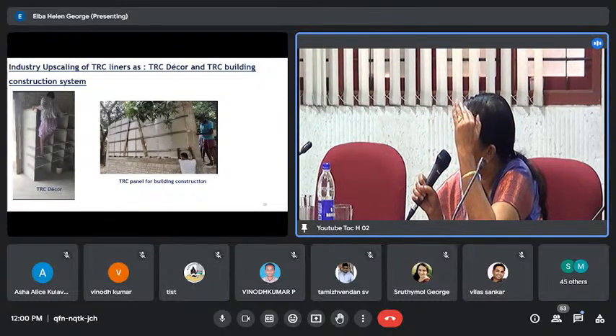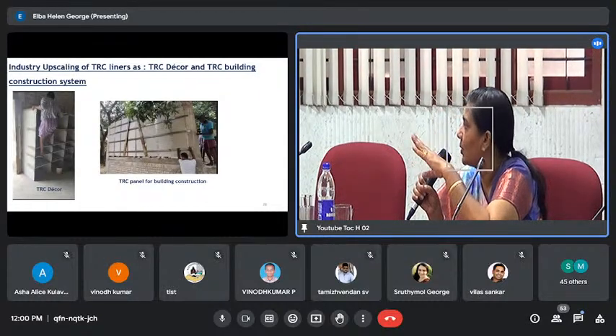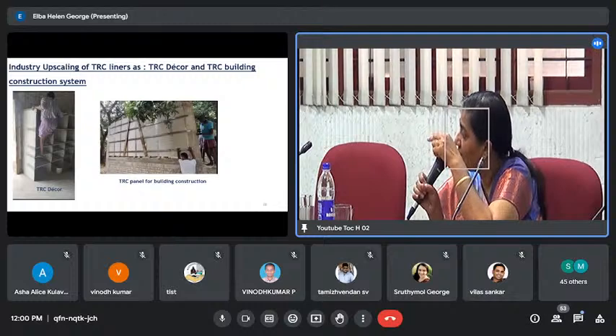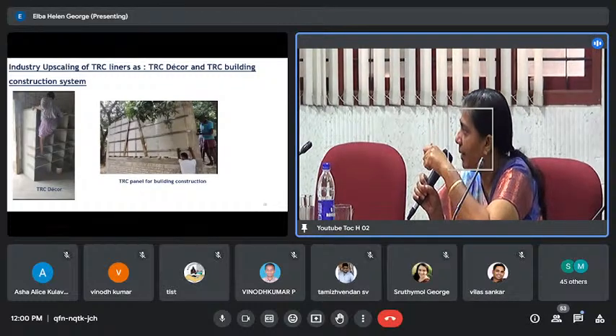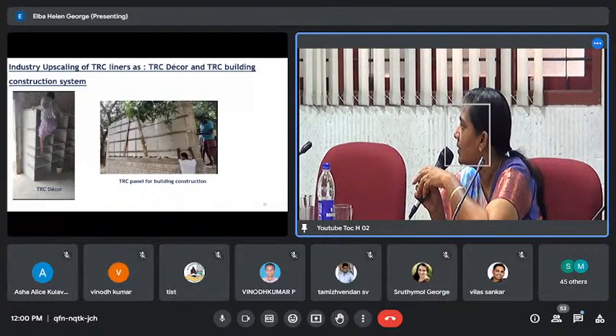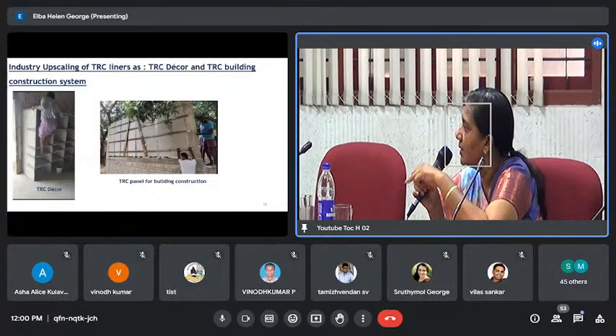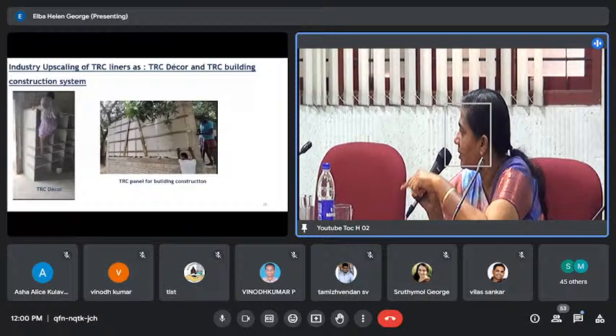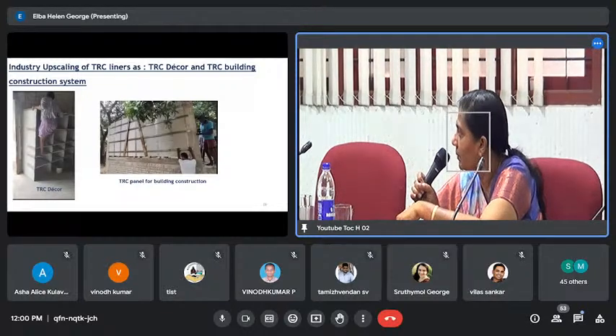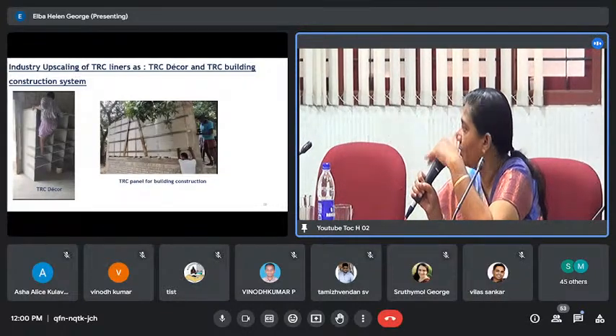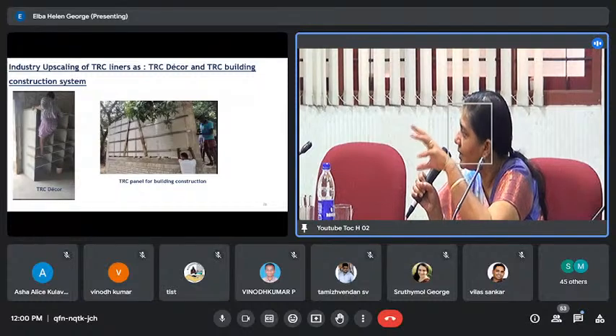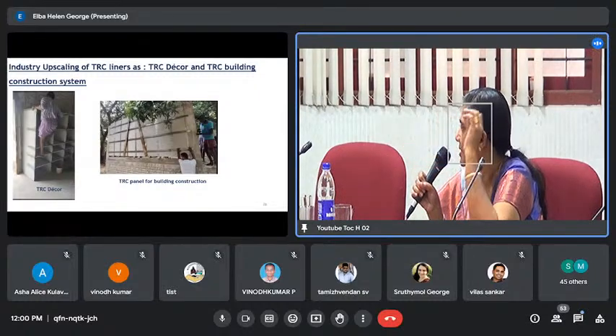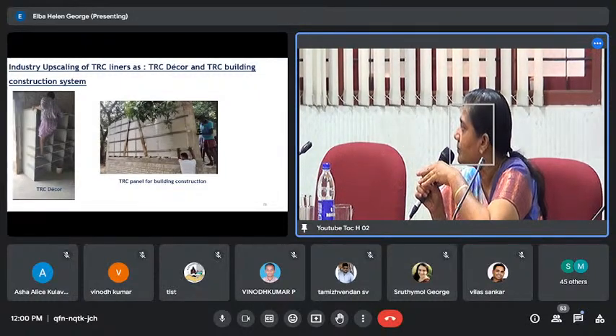Delamination of the concrete to TRC is not happening. But in the TRC, debonding between the textile layers and binder can happen if the number of layers is more than 4 in particular cases. Because if a binder has a bond strength above around 2.4 MPa, it will not debond from the concrete. So if your binder has that much bond strength, the chances of debonding are less. No problem, additional safety.